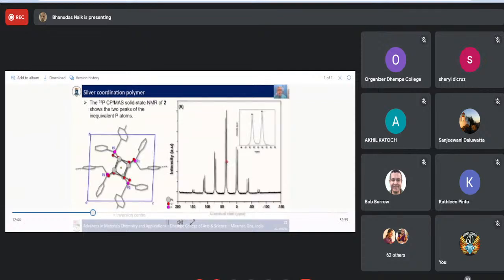We took the opportunity to do a phosphorus-31 cross-polarized magic angle spinning solid state NMR of 2, which is a silver compound, and you can see the 2 peaks here. You don't see any silver-phosphorus coupling in this spectrum. And here you can see you have 2 unique phosphorus atoms in the crystal structure, and they're really quite resolved in the solid state. Even though they're the same phosphonate group, the environment is different, and that's enough to have a very slight chemical shift difference between the 2.